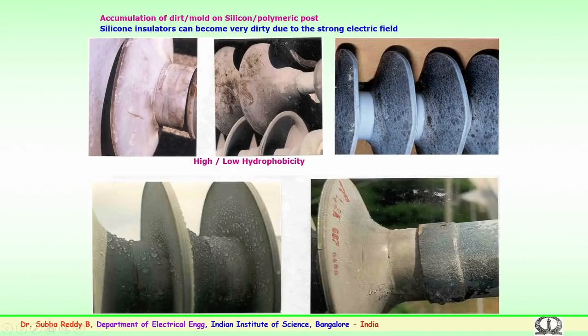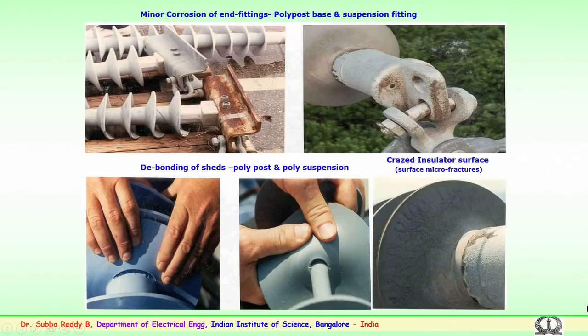Now, a lot of technology improvements have happened in the material aspects and also in the manufacturing processes. Here you see the corrosion of the end fittings. This could lead to failures of post insulators or suspension type insulators. Similarly, there is debonding of the sheds. If it is not properly taken care of during the manufacturing period, this debonding of the sheds could lead to failures over a period of time.